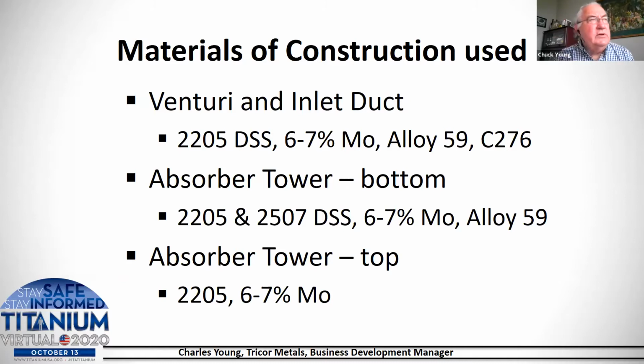Materials of construction used, and these results are from the survey, so these are the initial scrubbers that were put in over the last, say, 10 years. And one thing to point out here is that these are all nickel or stainless alloys. It shows that the nickel and stainless industry is very well known in these types of markets, and it also shows that they try to use the lowest and least expensive nickel alloy first, and then they go up into higher alloys, just like they did back in the flue gas desulfurization market for coal-fired power plants back in the 80s and 90s and early 2000s.